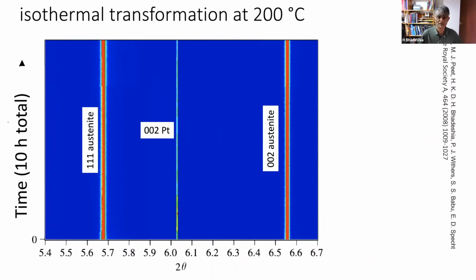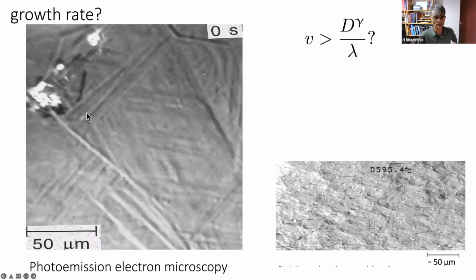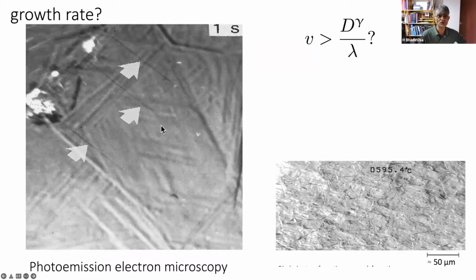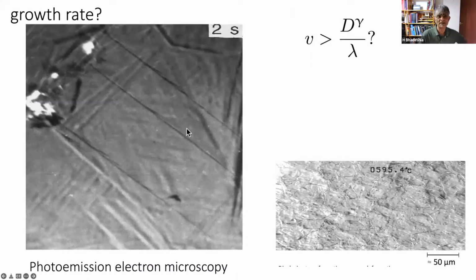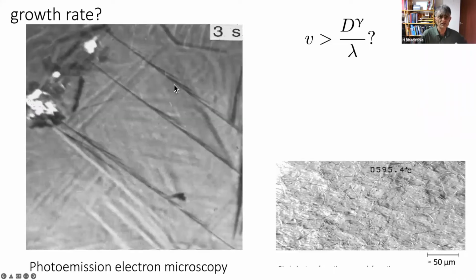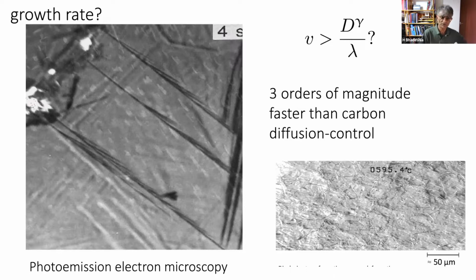Okay, going back to the measurement of the growth rate of an individual platelet, there is a technique known as photoemission electron microscopy at the University of Neuchâtel in Switzerland, which we used, where you can take a bulk specimen, heat it up to whatever temperature you want, austenitize it, and you shine ultraviolet light on it, which causes it to emit electrons, which are then collected by the magnetic lenses to form an image in the conventional way. And I'm going to show you a sequence of 4 images using the photoemission electron microscope. And you can see the growth of individual platelets and then other platelets forming, okay? Just as I showed in the transmission electron microscopy. So you can measure the growth rate of individual platelets.